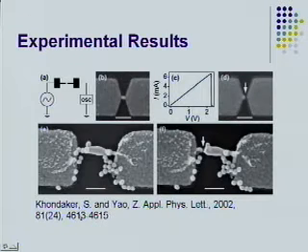And then there's this study that's been fairly recent, which is kind of interesting. They trap gold particles also, and they get these gold clusters. Then they try to get these nanoscale break junctions, and they electromigrate out a gap. As you can see here, in C they show the ramp that they apply, and all of a sudden the current stops once you break that junction. And you can see at the bottom how they actually melt the colloid due to the high current. And then you get this little junction there. Go ahead.